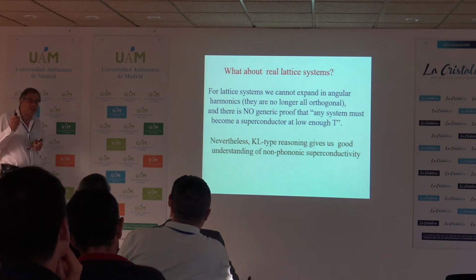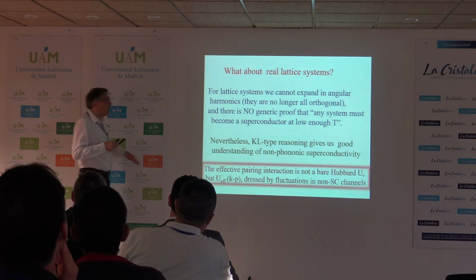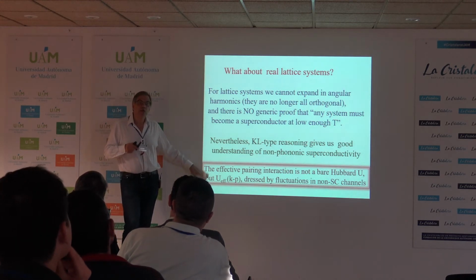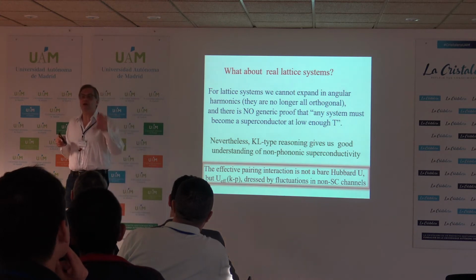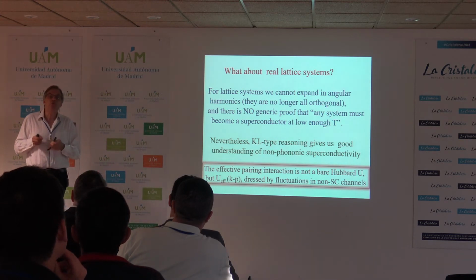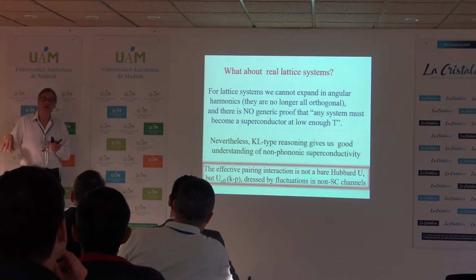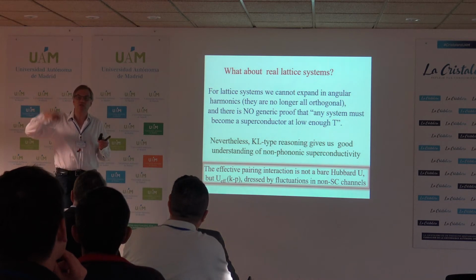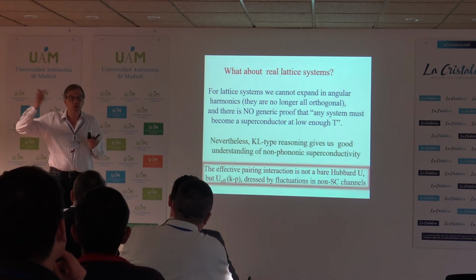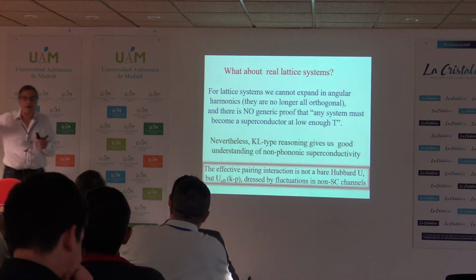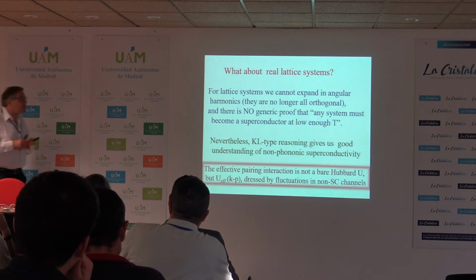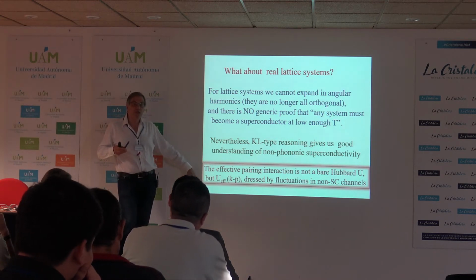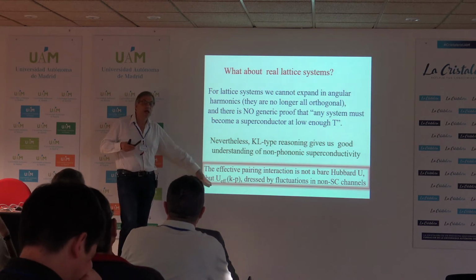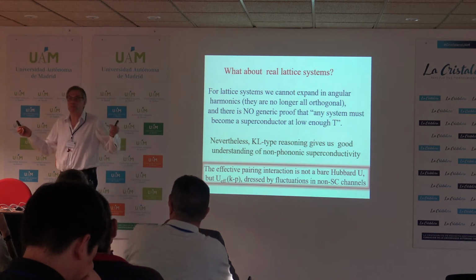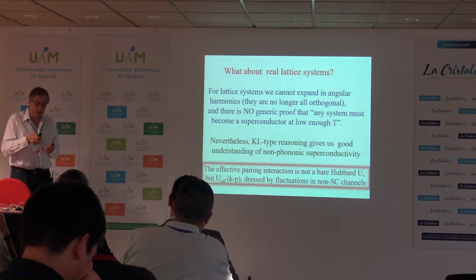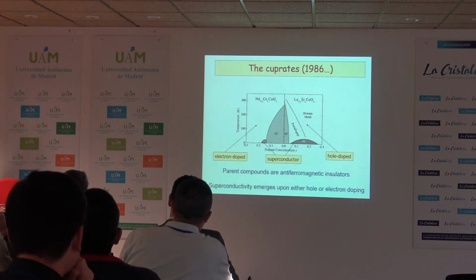And by elements of Kohn-Luttinger physics, I mean this: if you talk about pairing interaction, you don't take your Hubbard U as the interaction. You dress it up by fluctuations in non-superconducting channels. Because Kohn-Luttinger physics is that you take the pairing interaction and dress it up by stuff that gives rise to screening of Coulomb interaction, which are corrections in the particle-hole chain. If you apply the same reasoning, then you have to include that screening or that renormalization into consideration and deal with an effective interaction, which of course becomes a function of momentum transfer, as the pair interaction. And let's see how it works for particular cases.